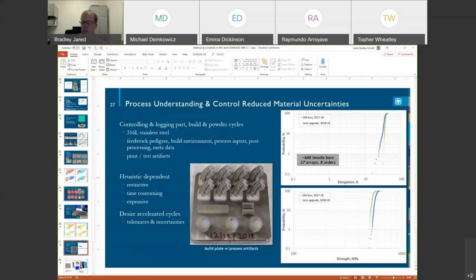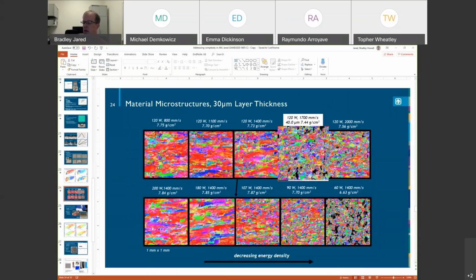Then the material would act like any other material that is limited by the statistical distribution of defects. Like in a ceramic, you have a lot of variability because ultimately fracture strength is going to be controlled by the population of defects that you have, right? And in an additive manufactured metal part, under tension, if you are in a region of the process space where it's more likely to have porosity of different kinds, it's probably more likely that you're going to have a distribution of performance, because the distribution is not going to be controlled by the intrinsic properties of the material, but by a particular instance of defect populations in that material.